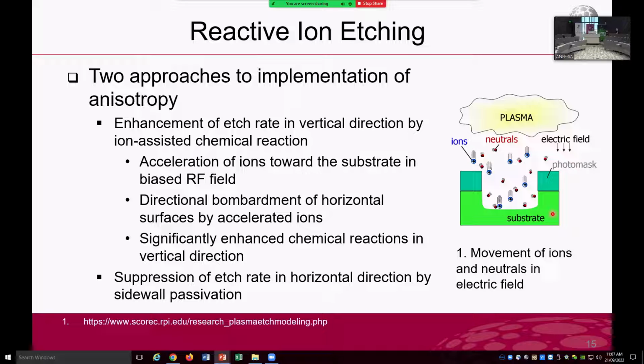Then what's going to happen? Only on this horizontal surface will the etch rate be enhanced through the chemical reaction. So this ion bombardment just enhances the chemical reaction in the vertical direction. Right? That's the ion-assisted chemical reaction. By using this process, we can improve the etch rate in the vertical direction without causing etching on the sidewalls. Right? That's one way of implementing vertical sidewalls, anisotropy, in dry etching, reactive ion etching. And another way is passivation of sidewalls.